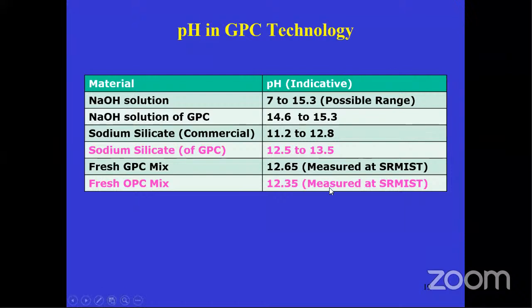We made a geopolymer concrete mix and studied the pH; the earlier figures were for the solution mix. After mixing with concrete, the pH in the concrete is 12.65, which is similar to ordinary concrete. So don't say that geopolymer concrete is highly alkaline; that is wrong. It is proved in this slide.